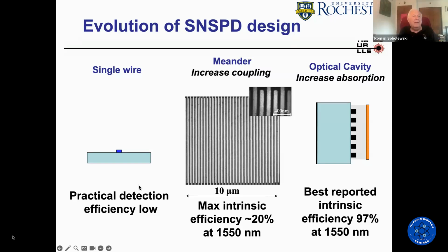Because my niobium nitride film is still extremely thin, it didn't absorb all the photons, and there was a fill factor of about 50%. So there were still some photons which would travel through the detector unrecorded. So finally, the current commercial devices will have a resonant cavity, and this way photons are kept in that resonant cavity, and efficiency can be like 97%.